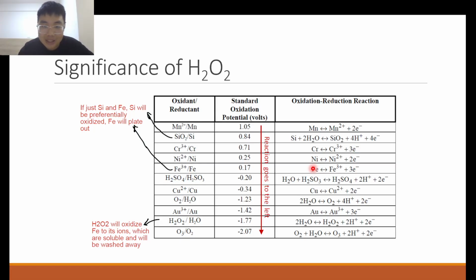And so what happens is that Fe, which is iron, gets plated up, it gets precipitated on your silicon surface. However, if you have H2O2, we see that H2O2 is preferentially reduced over Fe3+, because it has a more negative oxidation potential than your Fe3+, Fe couple. So your H2O2 will be reduced and your Fe will be oxidized to Fe3+.